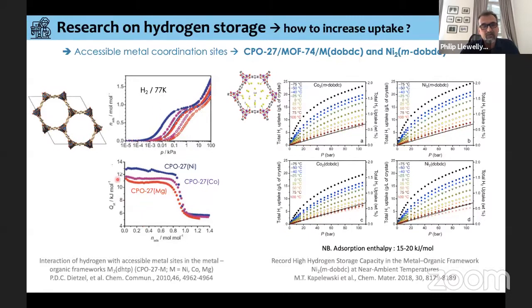This work shows the adsorption of hydrogen as a function of pressure. This is in a log scale here, and we can see the uptake in 2 steps. This first step here is due to the adsorption close to these metal centers. What is then possible to do is to calculate the heats of adsorption, or the energies of adsorption. Here we have the energies of adsorption in kilojoules per mole as a function of uptake. We can see that for this MOF made with different nodes, with magnesium, cobalt, and nickel, we get slightly different hydrogen adsorption energies.